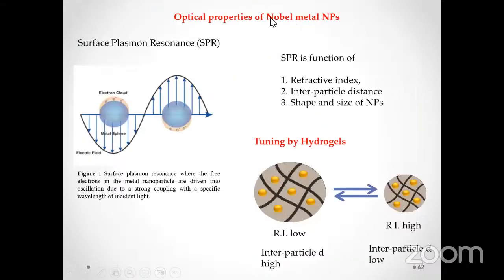And here are the optical properties of these noble metal nanoparticles. When we prepare noble metal nanoparticles such as silver and gold in the hydrogel networks, these nanoparticles show optical response, which means that when light falls on these systems, they give some response. That response appears in the form of change in their lambda max, or in the form of change in their absorption intensity. This optical property is due to their surface plasmon resonance, which is the collective oscillation of the electrons present on the surface of the metal nanoparticles. This surface plasmon resonance is a function of interparticle distance. This is a function of refractive index. This is also a function of shape and size of the nanoparticles.